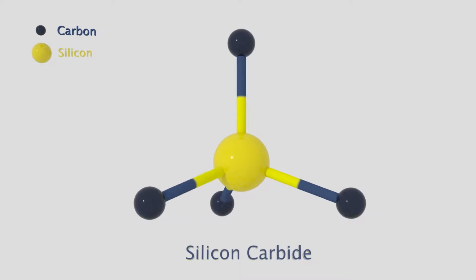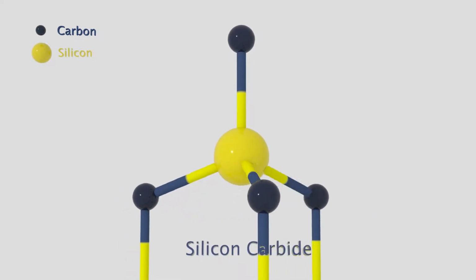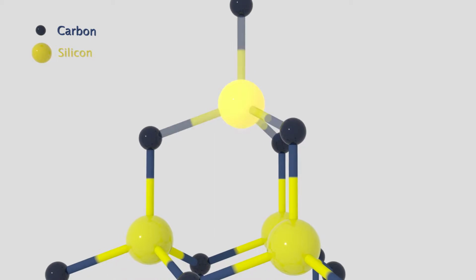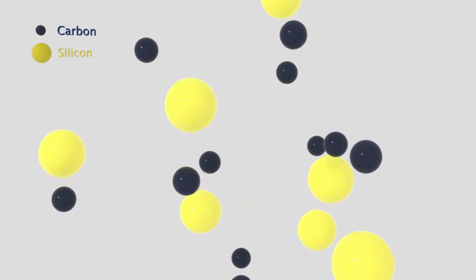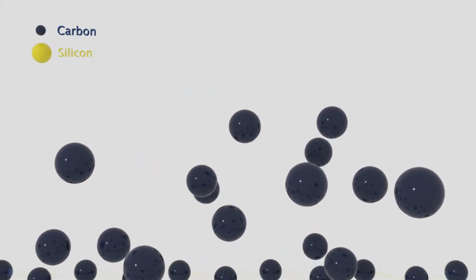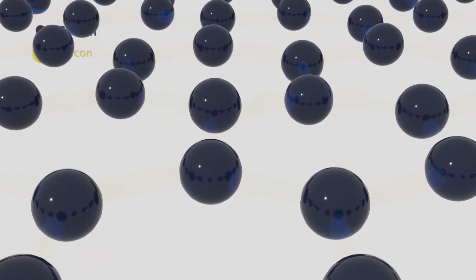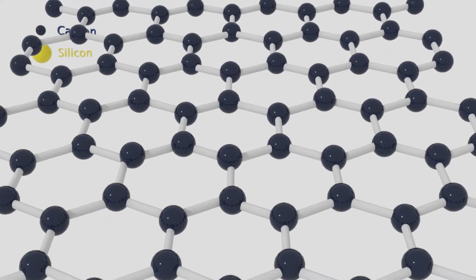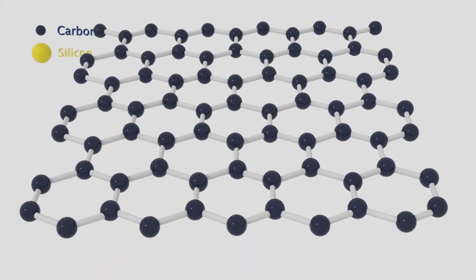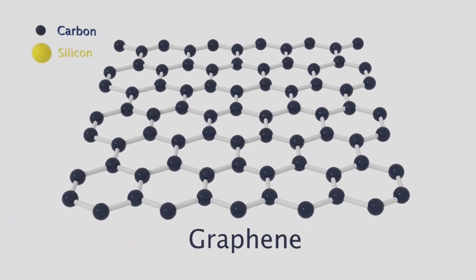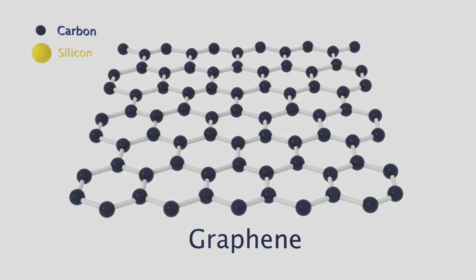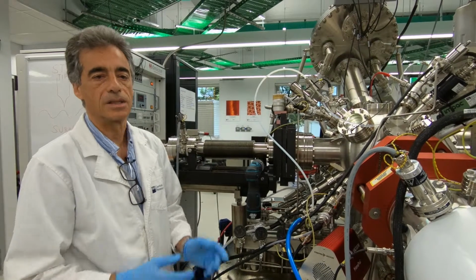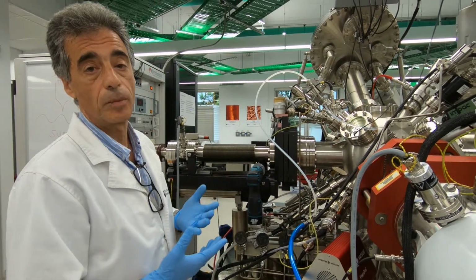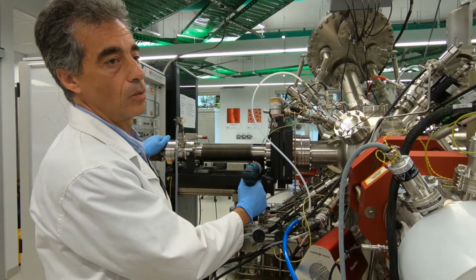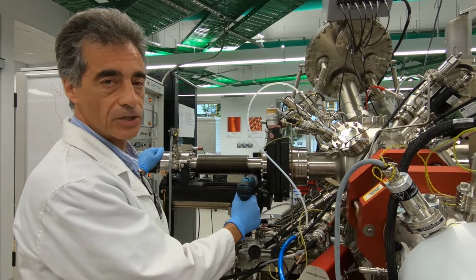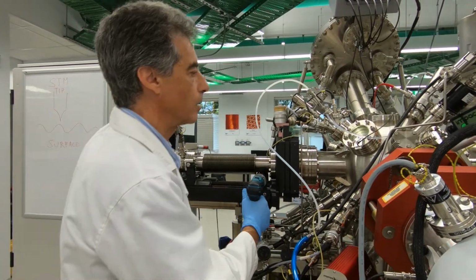Graphene is formed from silicon carbide when it is heated to about 1200 degrees. As the silicon atoms leave the surface, the residual carbon atoms rearrange into a hexagonal network. The longer the heating and the higher the temperature, the more silicon leaves the silicon carbide and the more layers of graphene are formed. Now that our sample is well cooked and hopefully we have prepared graphene, we are going to move the sample from the preparation position to the STM by moving this transfer arm.